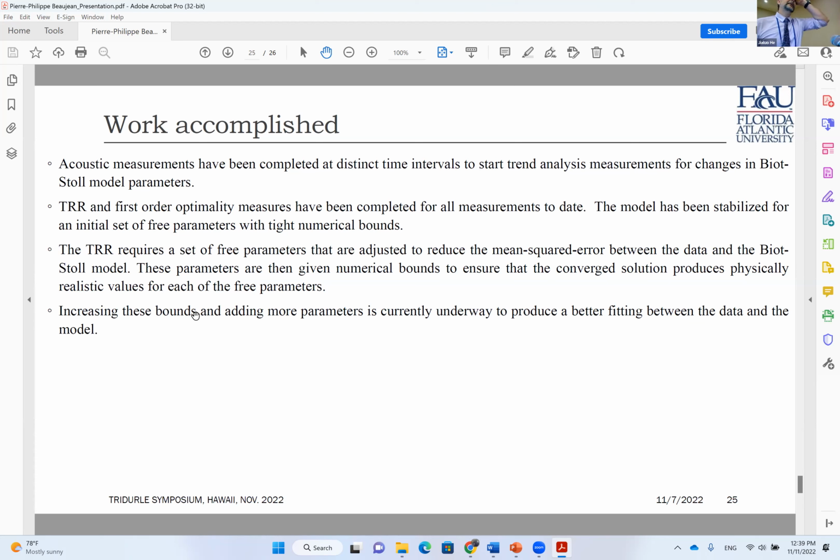Yes, sir. I'm sorry, I missed the beginning. What was the frequency? Right now we operate at 500 kilohertz. This is an immersed transducer, but an oblique transmission transducer with surface wave could be handled by this model as well, because this model handles compressional waves and shear waves.